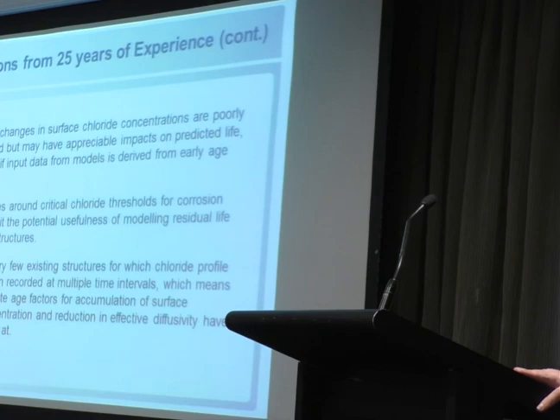The temporal changes in surface chloride concentrations are poorly understood, but I think I've demonstrated that they have appreciable impact on your predicted life, and that's especially true if you're using data derived from early age studies, and lots of the Fick's law type diffusion models are based on early age studies, so just 6 months or up to 2 years. The uncertainties around the critical chloride thresholds for corrosion estimation, at least to me, limit the potential usefulness of these for modelling residual life of existing structures.